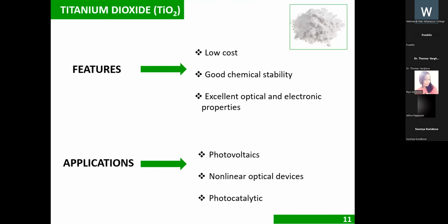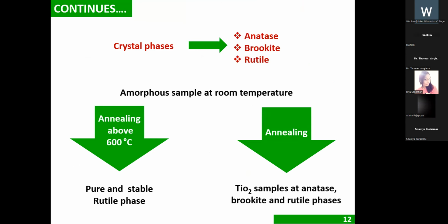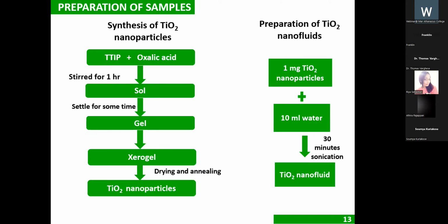Here I took TiO2 for the study. TiO2 has eminent features and applications in a variety of fields, including photovoltaics, photocatalysis, nonlinear optical devices, etc. It possesses three different crystal phases: anatase, brookite, and rutile. Usually, it shows an amorphous nature at room temperature. And when we anneal the sample, we get the anatase, brookite, and rutile phases. Annealing above 600 degrees Celsius, at high temperature, will give the pure and stable rutile phase of TiO2.